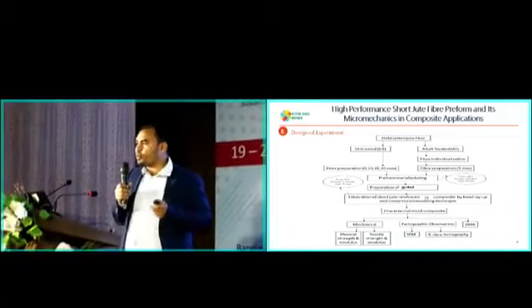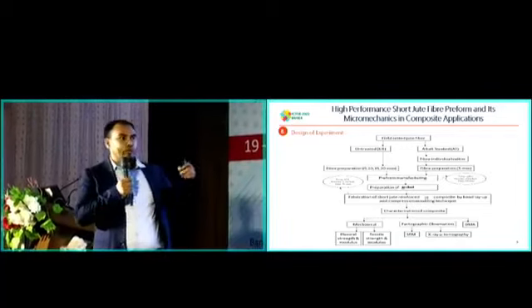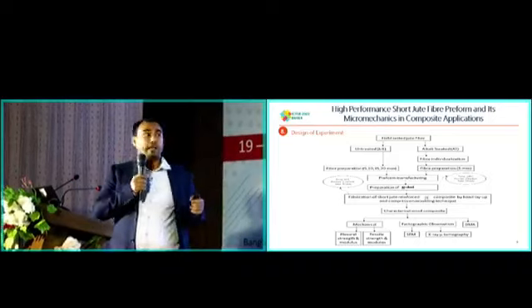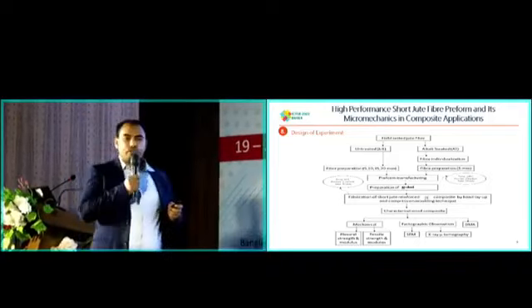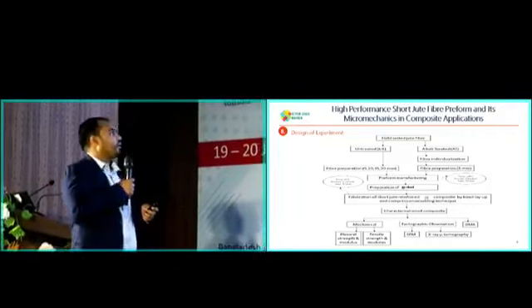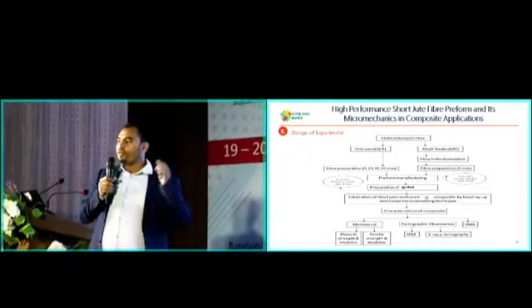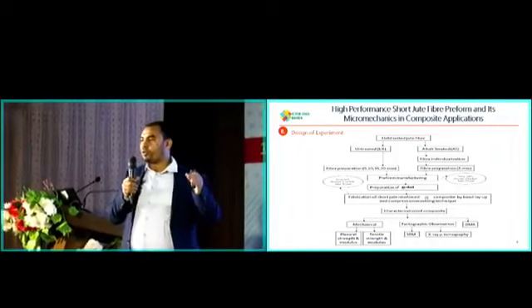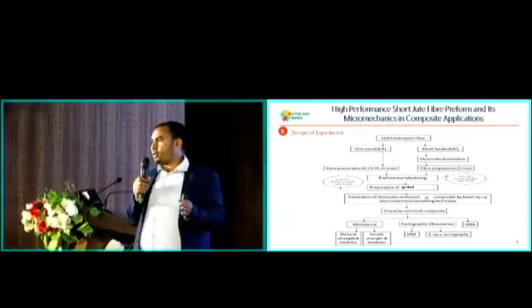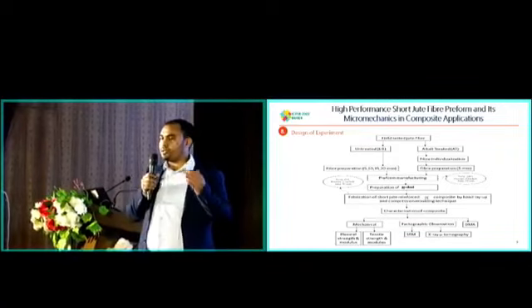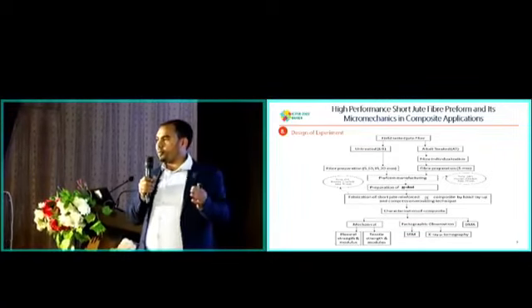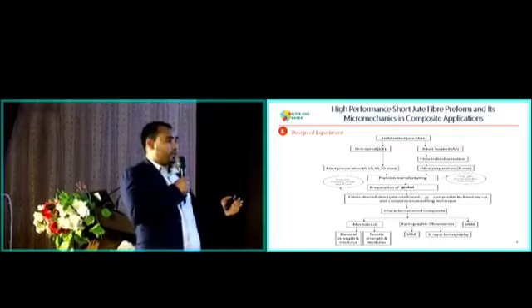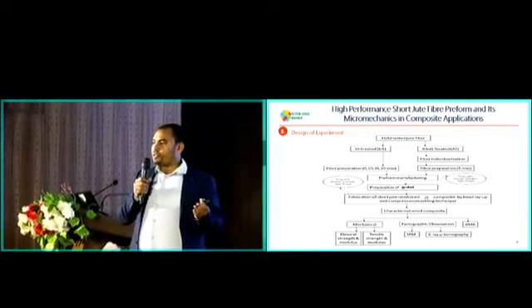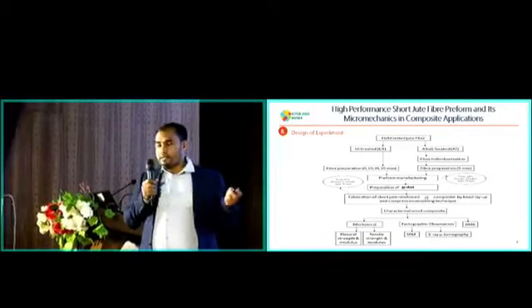Obviously, you have to design your experiment. So by considering all the critical points and challenges, we decided to use field-retted jute fibers, and then we treat the fibers and also leave some fibers untreated. So with control and uncontrolled, we adopted different mechanical extraction processes and chemical treatment, without treatment and with treatment. Finally, we characterized the materials, developed the composite, tested it, and analyzed the results.